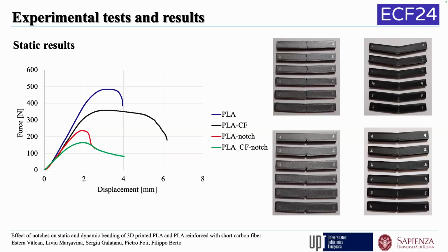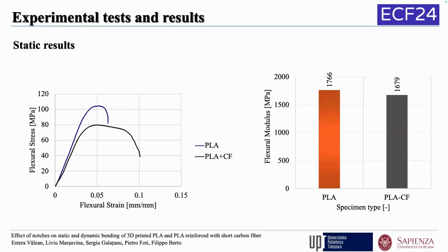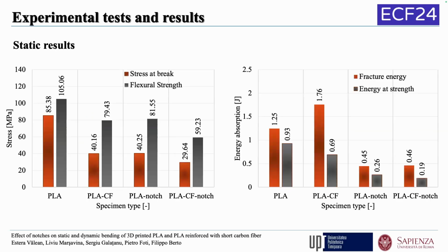So some results for the static test: we got the same results as in the case of the tensile test. The higher strength was obtained for the PLA compared with PLA reinforced. The only property that is higher for the reinforced PLA is the energy of fracture, the area under the curve, which is higher in both cases, in unnotched and also in notched specimens. So we determined the flexural modulus. There are not so big differences in flexural modulus. It's around 1.76 gigapascal for PLA and 1.68 gigapascal for PLA reinforced with carbon fiber.